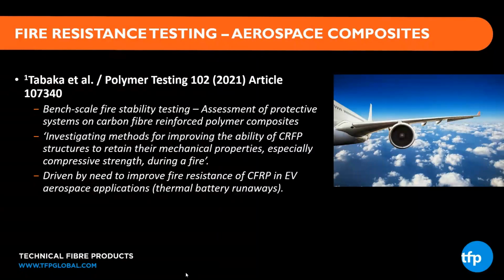So the title of this paper was Bench Scale Fire Stability Testing, an Assessment of Protective Systems on Carbon Fiber Reinforced Polymer Composites. And really the rationale behind it was investigating methods for improving the ability of CFRP structures to retain their mechanical properties, especially compressive strength, during a fire. And this was driven by the need to improve fire resistance of CFRP in EV aerospace applications, so in the case of thermal battery runaways. So it dovetails nicely with the study that Scott has just summarized.